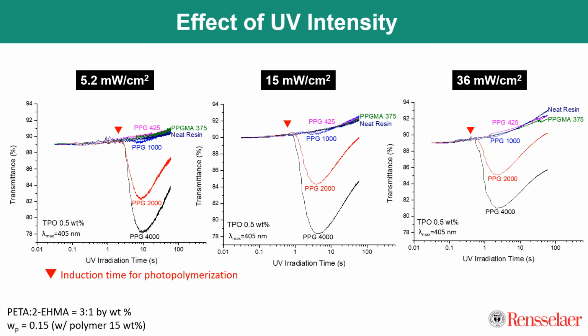And we expect this to happen because at a higher UV intensity, you have more photons being irradiated into the sample. So we have more photopolymerization happening at a faster rate, and these polymer additive molecules are essentially getting entrapped in the quickly developing polymer network, and they're not able to phase separate out as efficiently.